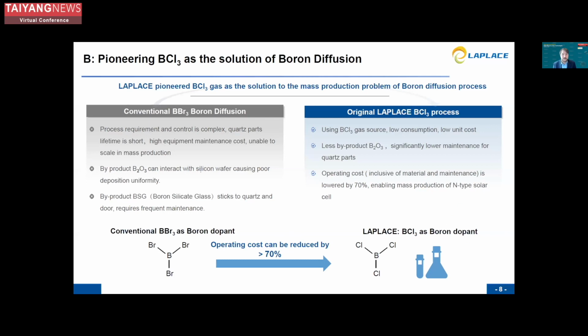We also pioneered this BCl3 transition. When we moved from PERC to TOPCon, one of the big issues was the boron diffusion, and to get good homogeneities in large batches and reproducibility. By using BCl3 as a gas source, we could lower the consumption, and we also could lower the byproduct B2O3, which significantly lowers the maintenance for the quartz parts. With these two effects, we were able to reduce the operating costs for the boron diffusion by 70%, which was a big driver to make the TOPCon possible, or at least economical.